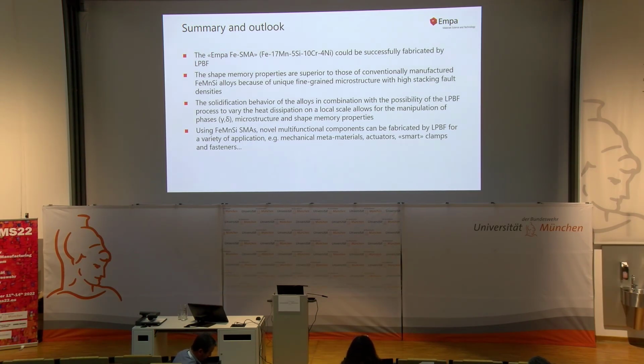which we could find out in our detailed studies. And the special solidification behavior and phase transformation behavior allows us, well, to play with the microstructure. So it's not random. Apparently we can control that. We have nice possibilities which we have to further investigate.